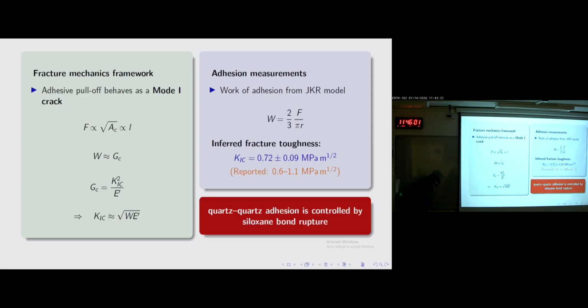If you look at it from the side, it kind of looks like a mode 1 crack, right? We're going to propagate a crack while I'm pulling off this tape. Same idea. If we think of adhesion or pulling off the contact as a mode 1 crack, then we can think of the work needed to detach or start detaching the nano-indenter contact as the critical energy release rate, G. Energy release rate is just the work required to start extending a crack in mode 1. And in mode 1, that is what we know from fracture mechanics.